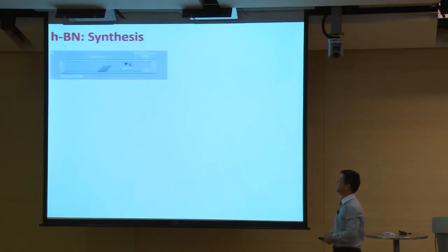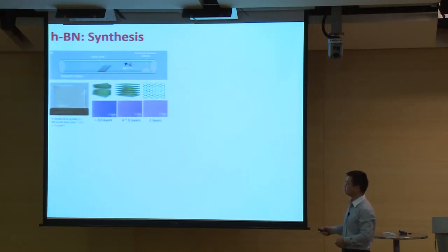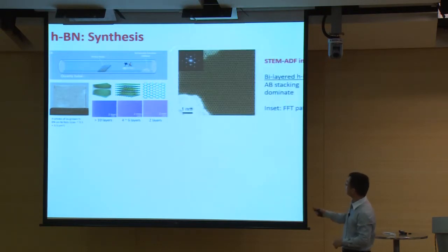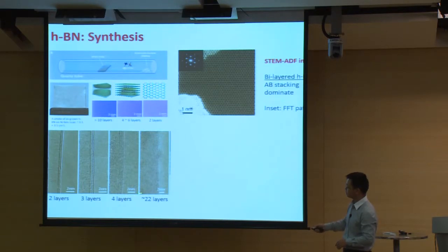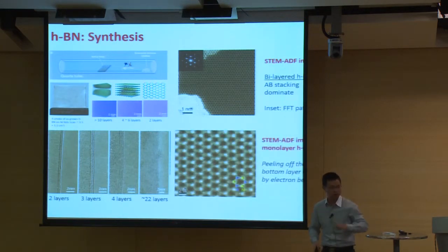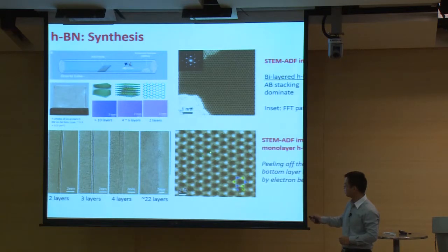Okay. For the synthesis of boron nitride, we use ammonia borane as the precursor and copper and nickel foil as the substrate. We have spent a few years improving the quality and controlling the thickness of this material, from the bulk one to few layers, down to double layers of boron nitride. And this is the STEM imaging showing the double layers of boron nitride, and also you can see the different layers, from more than 20 layers, 4 layers, 3 and 2 layers of boron nitride. And if we can peel off the top layer of boron nitride, actually we can get a defect-free monolayer boron nitride with these bright dot nitrogen atoms and these dark site boron atoms.